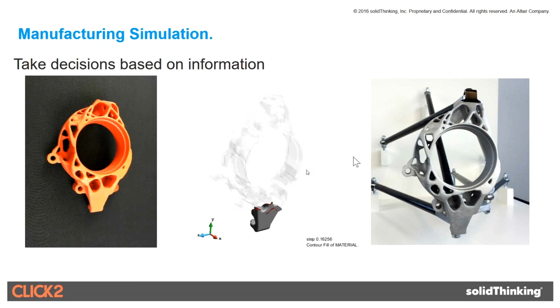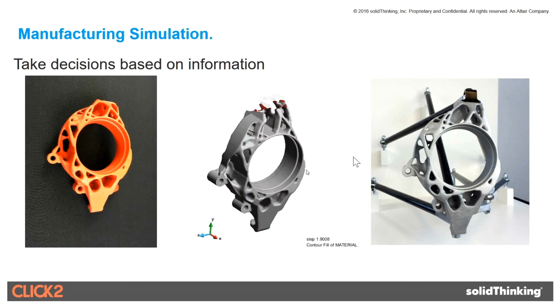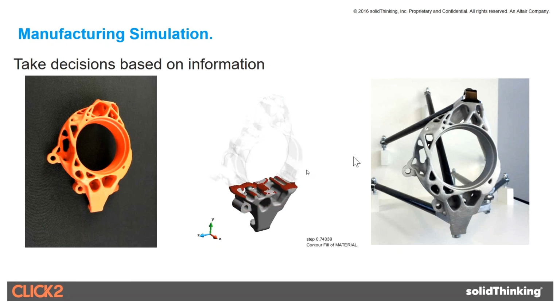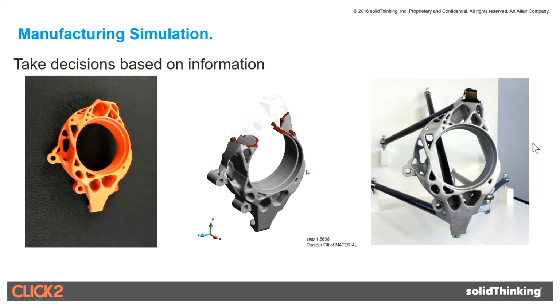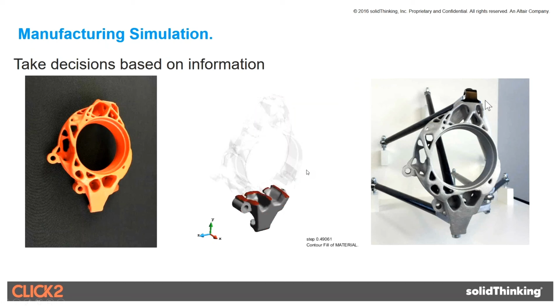We printed, but in this case, we 3D printed using a voxel jet printer, and we printed it in PMMA material. It's a wax-like compound which melts, and you put it in the oven, and then you pour the cast. And on the right-hand side is the final casting that you see. In this case, the weight reduction was almost the same, but the performance was way, way better. Okay, so that's another way of looking at what we were able to achieve in this particular case.